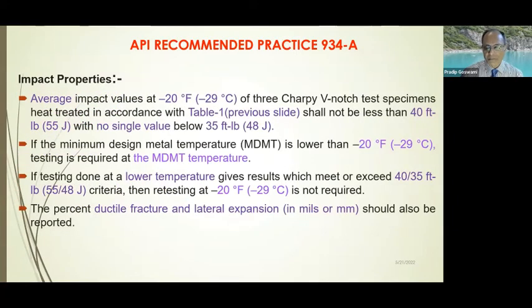Impact properties, that's a very critical aspect of these steels. And basically the requirement here is 40 foot-pounds or 55 joules average, with no single value below 35 foot-pounds or 48 joules at minus 29 degrees centigrade. That's a Charpy impact requirement. And at the same time, the percent of ductile fracture and the lateral expansion also have to be reported in the MTR.